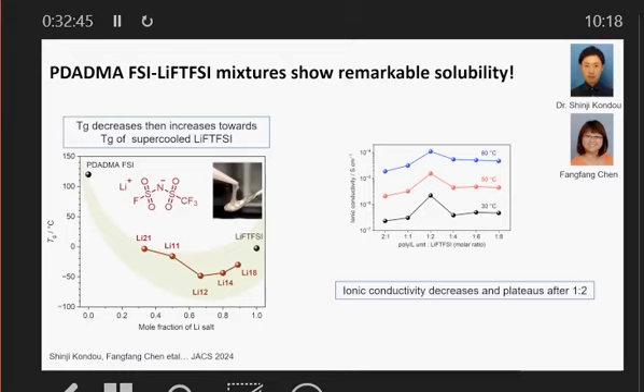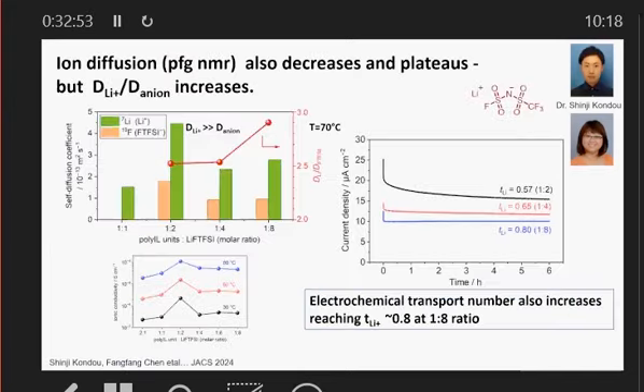We found the 1:2 was the best system, but maybe it wasn't so disappointing because it's not just conductivity that's important, it's also the transport number that's important. And so we measured the diffusion coefficients again. We measured the lithium diffusion coefficients, the green, and the orange is the anion diffusion coefficients.